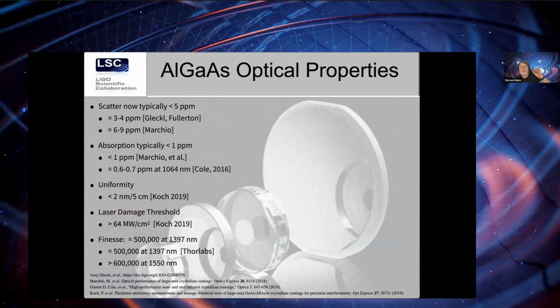So the one benefit that you have right now is that when you produce the AlGaAs coating, you're etching away and you have this etch layer. And so once you produce that, you can then go back through and ion polish. So if you just do that rough etch, then you have a sort of few nanometer variation. And now you can go back through and do an ion polish just like you do on the mirrors and get that down to the nanometer or sub-nanometer.